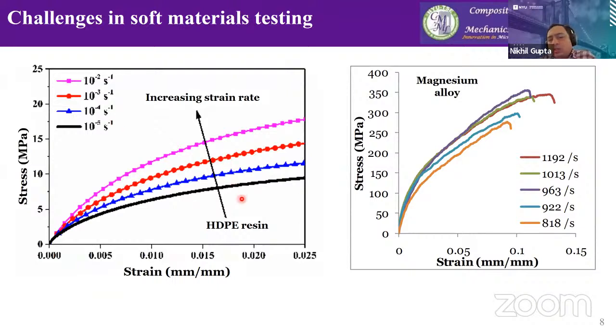But you can see that within these very slow strain rates, there is still remarkable strain rate sensitivity in this material. The black line here is 10 to the power minus 5, and this magenta line here is 10 to the power minus 2. And they are far apart. You can look at the numbers: at the strain of about 0.005, we are here at about 3 and here about 7. So in these cases, the values are quite different.